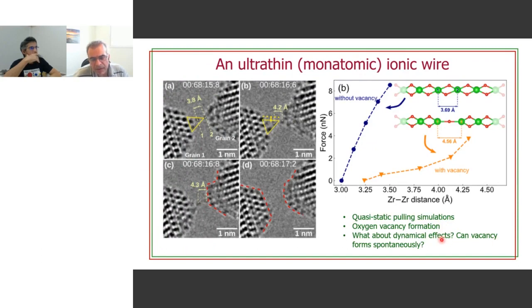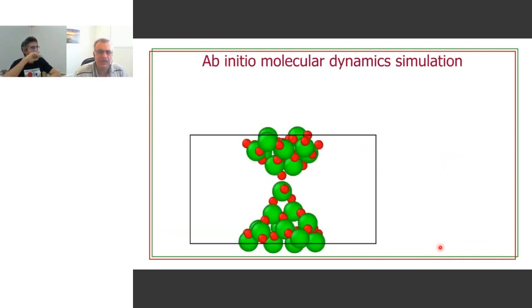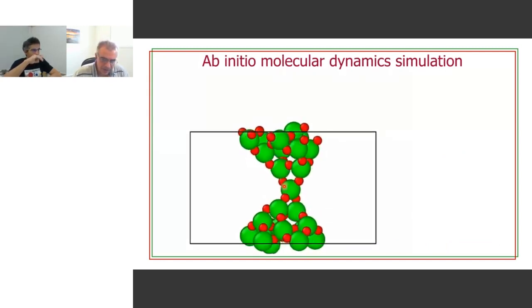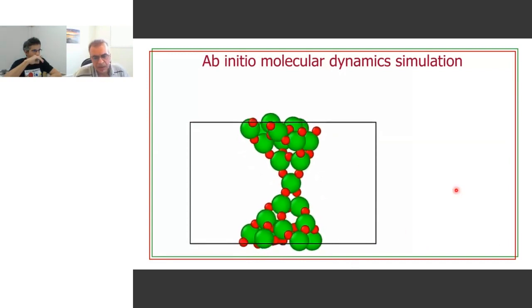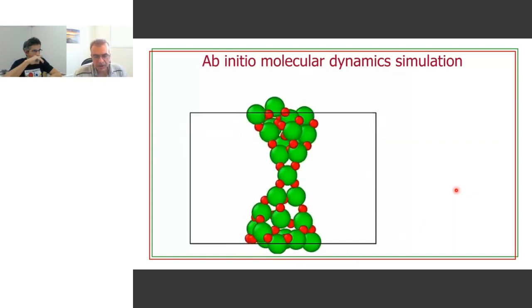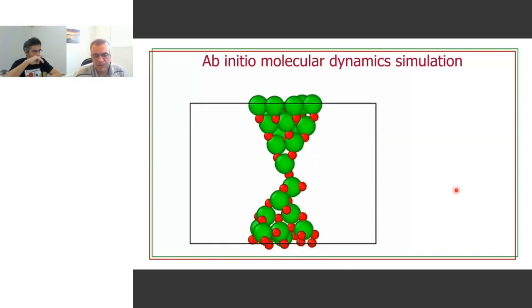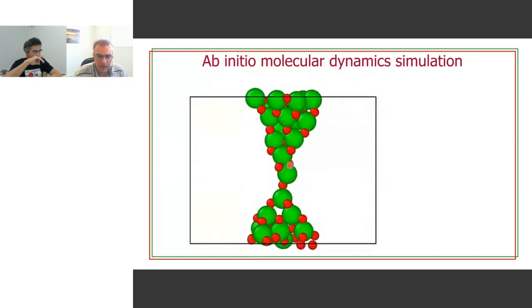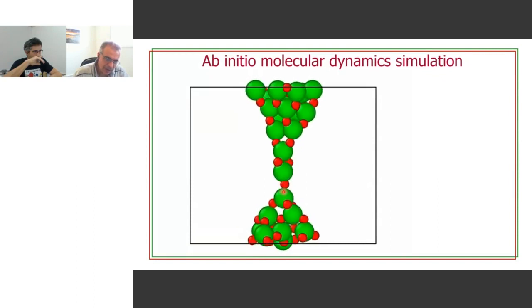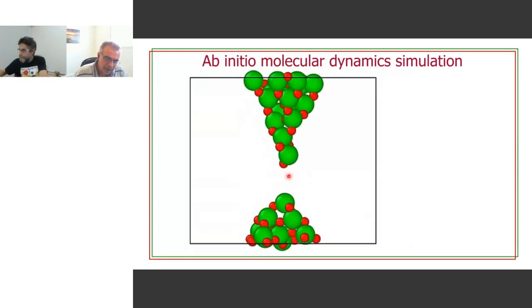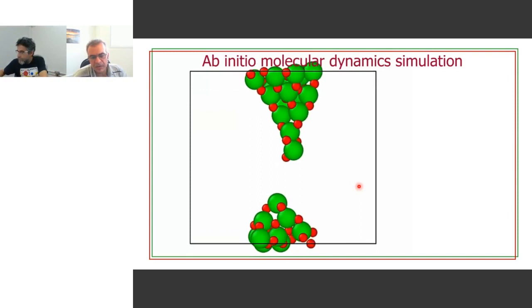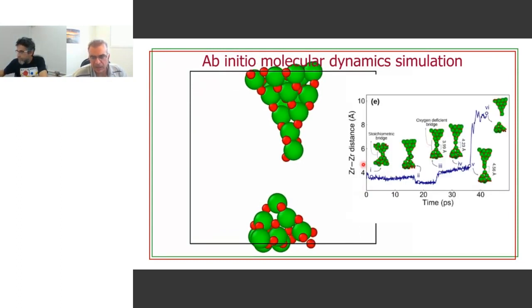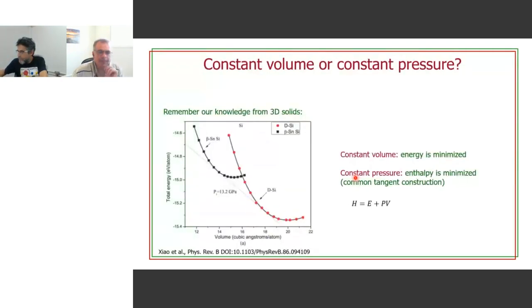So what about dynamical effects? How is this vacancy formed? Is it spontaneous, so the vacancy was already there, or where does it come from? To answer those questions, we did molecular dynamics simulations based on DFT, ab initio molecular dynamics simulations. We start with a very thin bridge, and you pull those two walls apart, and you can see that the atoms are moving, and eventually there are very complex atomic rearrangements and the formation of an oxygen vacancy. You see there's now a bridge between two zirconium atoms and one single oxygen. Now the vacancy moves to this point, and you see already here the non-stoichiometric piece of wire forming until it breaks. So it always goes through this vacancy formation before breaking, and the vacancy formation is the process leading to larger zirconium distances. So the experiments are quite well reproduced by theory.